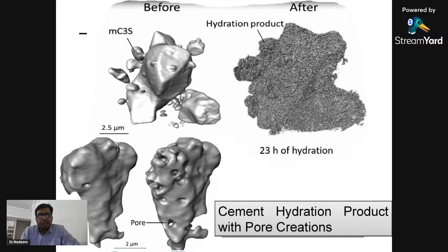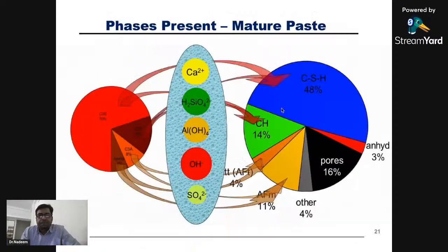And here you will be able to observe once these particles are reacting to form different compounds in the form of CSH, calcium hydroxide, and other compounds, and a lot of pores are being created in these particles. A lot of pores are being created.